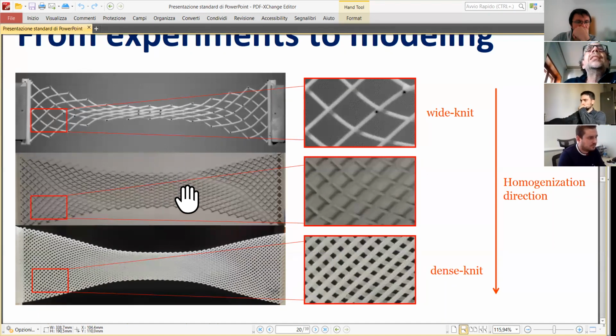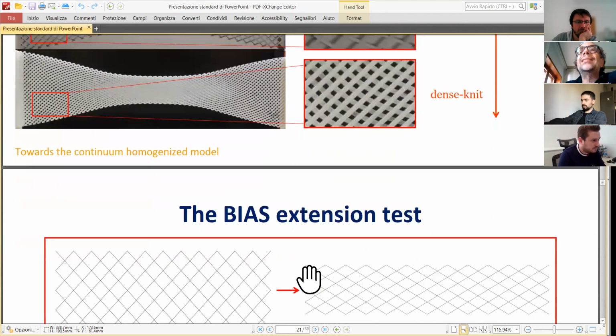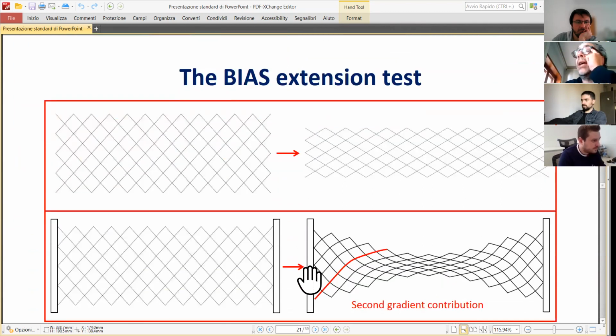If the mechanical properties and the geometrical properties of the considered architectures are well optimized, then your material remains in the elastic regime when it arrives at this level, okay? So you have a material which for certain displacements behaves like a second gradient material, so large elongations are allowed, and when you reach a given threshold, it stops behaving like a second gradient material and starts behaving as a standard one. Okay, what is happening? I'm not writing equations, but I'm telling you the interpretation of our results. When you have a pantographic microstructure like that, without lateral constraints, it elongates if the pivots are perfect in this way. So you have that from here to there, you go without deformation energy.